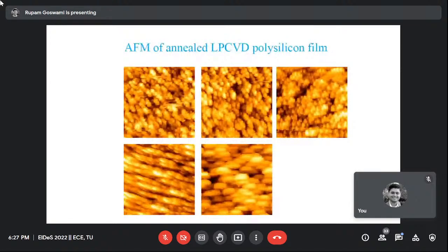Yes, so this is for the same previous profile. This is the grain growth. You see the as-deposited film in the left corner above, and the next is after annealing at 920 and 30. Then you can see the cluster formation of the grains started from here, and then the elongation effect is there at 1000 or 1020 and 1070. This is the ultimate grain size you can see, which is equivalent to the film thickness. This is called the normal grain growth mechanism. It is not affected by the dopant because doping is not there. This is as it is.